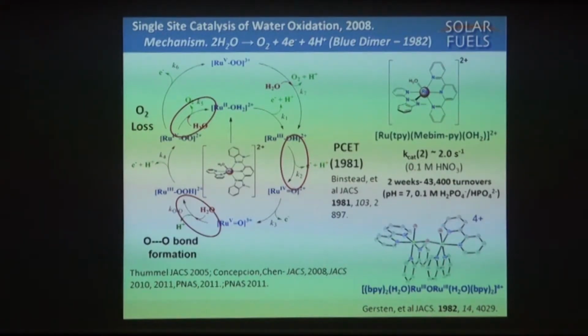But let's look at how this system works and gain some understanding about the underlying reactivity. This is an area that Ken has been a very significant figure in. Let's start with the complex, and let me focus for the moment on the ruthenium aqua bond. When you look at the periodic table and ask why people do so much ruthenium chemistry, it's in the second transition series, just below iron. It has this wonderful property that you can do the synthetic chemistry and make complexes, and after you make them in these coordination environments, they tend to be coordinatively stable in multiple oxidation states, all the way from 2 to 6. If you tried these tricks with iron, they simply wouldn't work. Iron complexes would fall apart. So there are special characteristics built into ruthenium that dictate why many people study these systems this way.